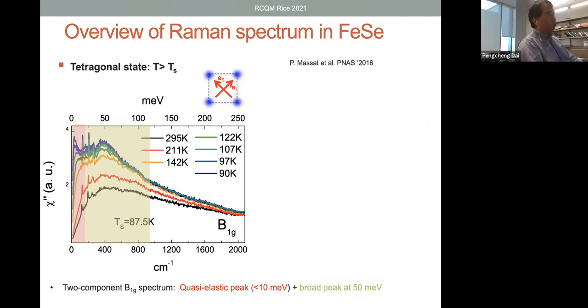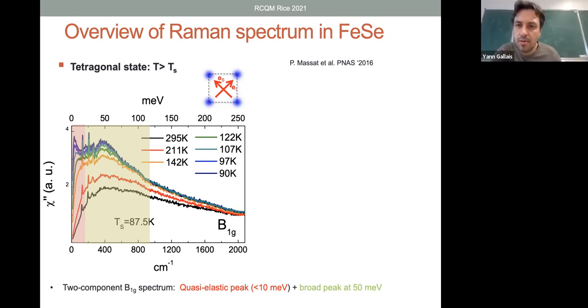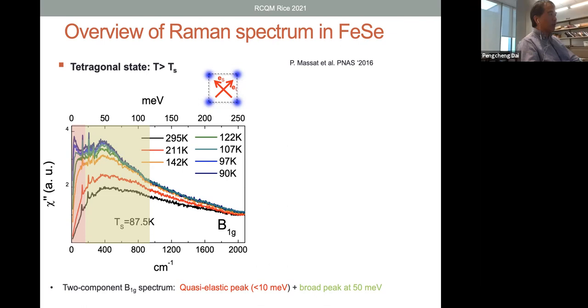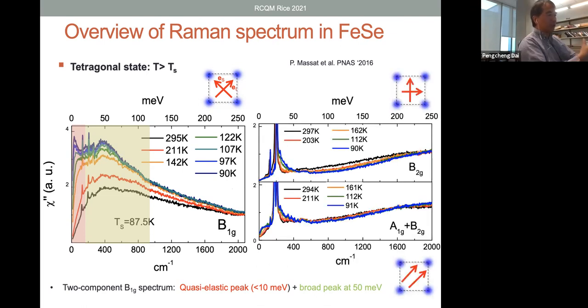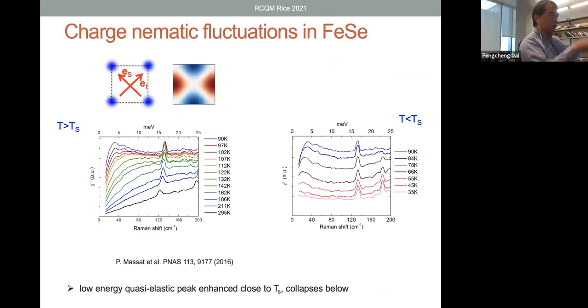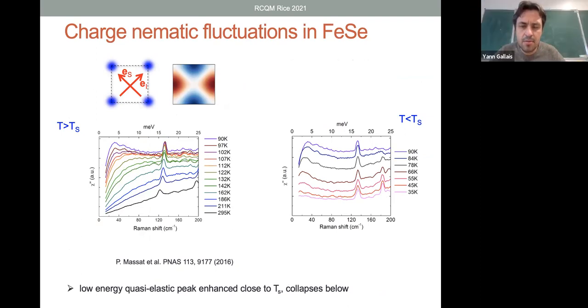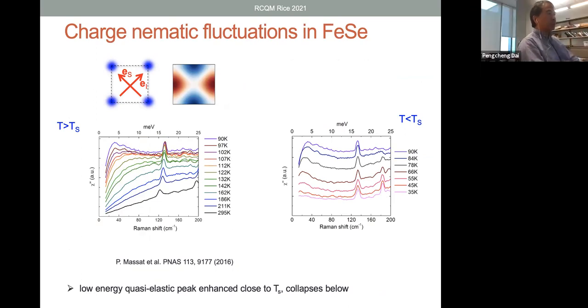I see. If you include up to like 70, 80 meV for the iron selenide, do you also see similar features, or is this feature gone? The susceptibility goes up and goes back down. If you analyze this Raman data like you plotted here, say below 80 meV, and compare the susceptibility between A and B axis, do you still have this Curie-Weiss-like temperature dependence, and then it goes down below TS? You had a plot where susceptibility goes up and goes down at TC. This basically measures the susceptibility difference between Q1 and Q2, right?